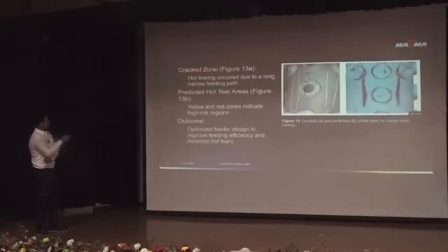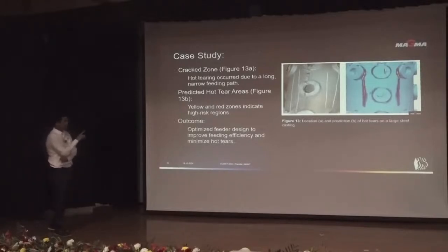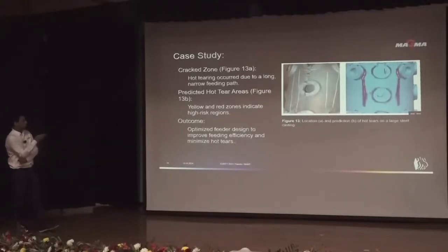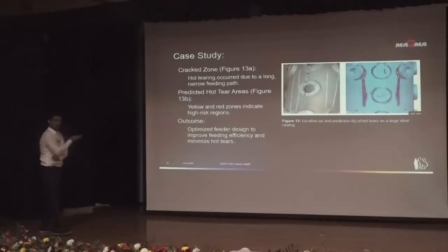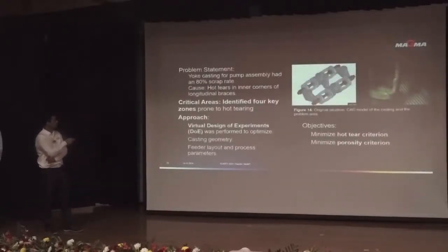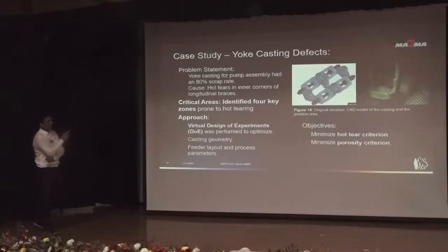So we have to pinpoint those areas. This is a case study where we were able to predict by simulations which regions the hot tears might form, and in actual we were getting the same results. What was the outcome? We improved the feeder design to increase the feeding efficiency, because narrow feeding paths were causing hot tears. Another case study is a yoke casting, where you can see there is a corner where we are getting hot tears.